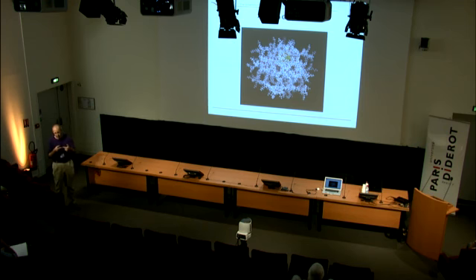And we want the metal ions only in the interior of the dendrimer, not on the exterior. If they coordinate to the exterior, they'll basically polymerize the dendrimers, and they'll just precipitate. So it's important that the peripheral groups be non-coordinating. But this is just to show you that there's easy access, almost unhindered access, we think, of small molecules to the surface of this particle through pretty big pores inside the dendrimer.